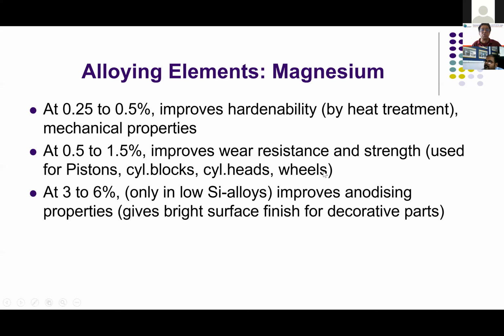This improves the hardenability. The most widely used alloy is LM25, where the silicon is about 6 to 7.5%, and magnesium is about 0.3 to 0.5. Right? It improves the hardenability.